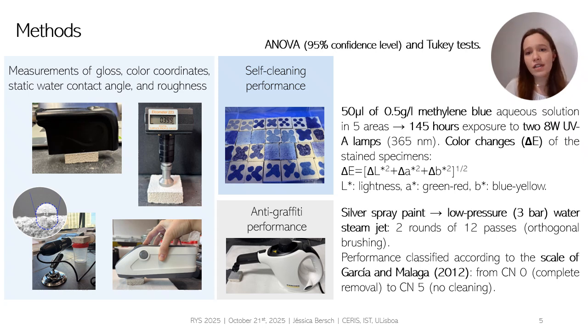The methodological framework consisted of a series of surface tests. We measured gloss, color coordinates, static water contact angle, and roughness. We have also studied self-cleaning and anti-graffiti performance. All the results that are discussed were evaluated with analysis of variance and Tukey tests.